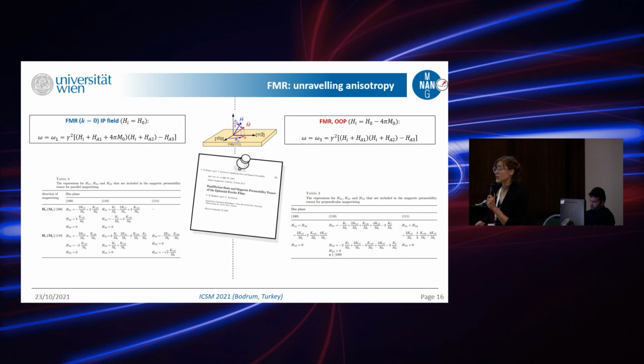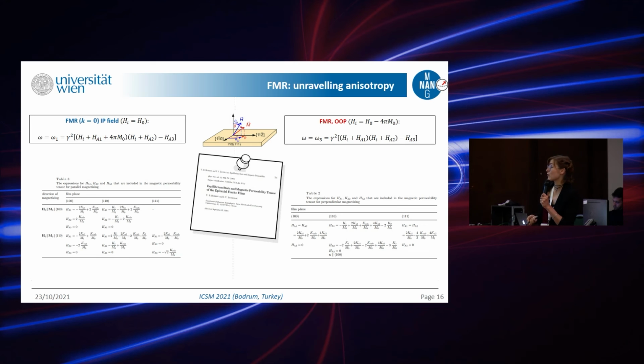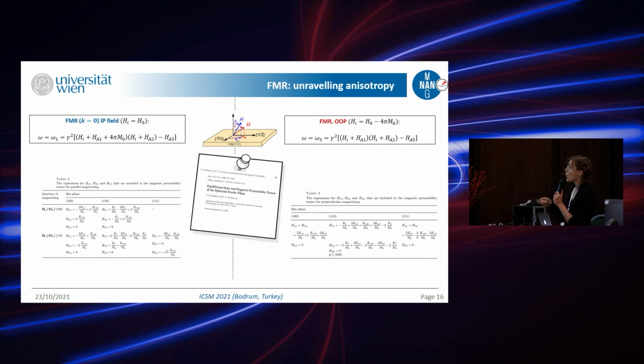And indeed, we find such a theory. It's from the group of Professor Zavislak from Kyiv, where you see the equation which depends on the anisotropy ansatz for the in-plane and out-of-plane. For both, these anisotropy ansatz depend on the crystallographic orientation of the substrate, so whether you have GGG 100, 111, or 110, and how you apply your magnetic field in the case of in-plane characterization. I can show you later if you're interested, I have a more precise analysis.